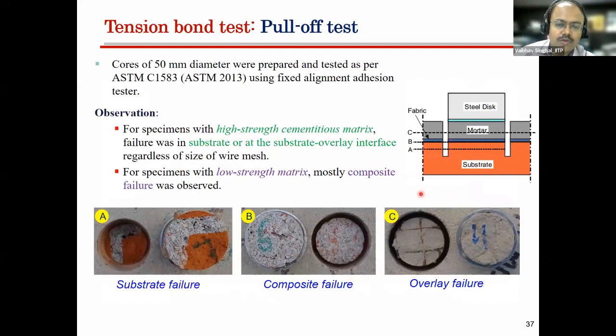Yes. So you can see this is the test which is done on the reinforced cementitious matrix applied over the masonry surface. So we can have different failure modes A, B, and C. So first is in the substrate. So the first failure mode we have observed in a few specimens is where the failure is seen from the substrate level. Then you can have the failure at the interface of your matrix, reinforcing material and the substrate. So this is kind of a composite failure. And then you can have also the failure of the matrix. So this is the failure of the matrix.